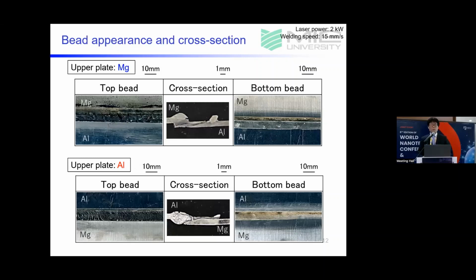These pictures show bead appearance and cross-section of welded joints with a laser power of 2 kilowatt and a welding speed of 15 millimeters per second. The upper table shows the condition with magnesium as the upper plate, and the lower table shows the condition with aluminum as the upper plate.